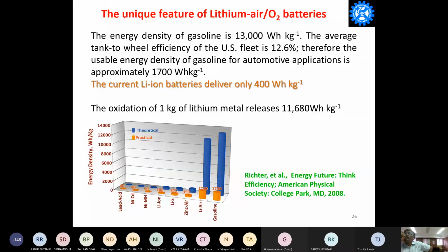The current lithium-ion batteries can deliver only 400 watt-hour per kg. On the other hand, if you oxidize 1 kilogram of lithium metal, it is capable of producing 11,680 watt-hour per kg. So the lithium air battery has a unique property which can deliver 11,680 watt-hour per kg theoretically. Even if you realize 15% of the theoretical capacity, you can simply replace the gasoline engine with lithium air batteries. But unfortunately, there are so many technological and scientific problems remaining that can be resolved only beyond 2050 or 60. So in the near future, you cannot use lithium air batteries.